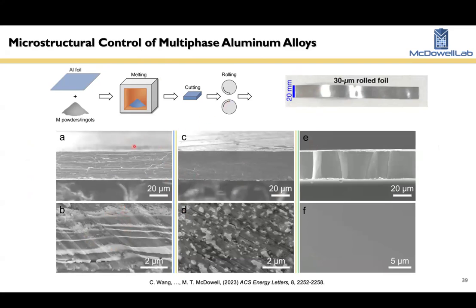So in particular, we focused on these multi-phase aluminum materials. So we start with aluminum, we mix other materials like tin or indium or zinc into it, we heat it, we cool it, and then we can roll it out as a foil. And you can see that we can define different sorts of microstructures. So here's a layered microstructure with tin and indium as a two-phase microstructure. Here's zinc, forms a particulate microstructure with an indium. And here's a solid solution. This is actually with gallium.